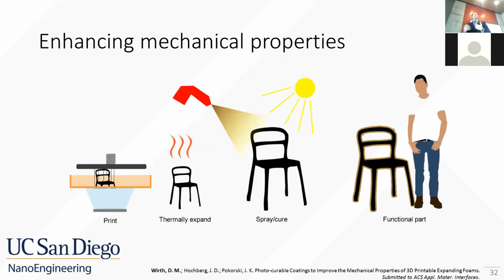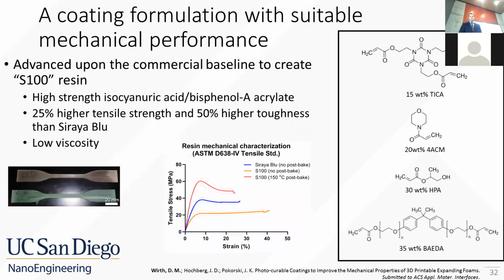The method we've come up with to do this is a two-part approach. We print the structures at small scale, thermally expand them, and then spray them with an ultraviolet-cured photocurable high toughness resin, arriving at a functional part with a little bit higher strength.